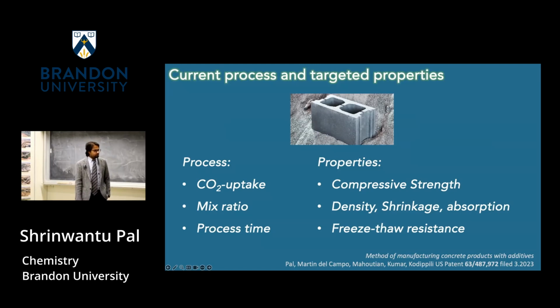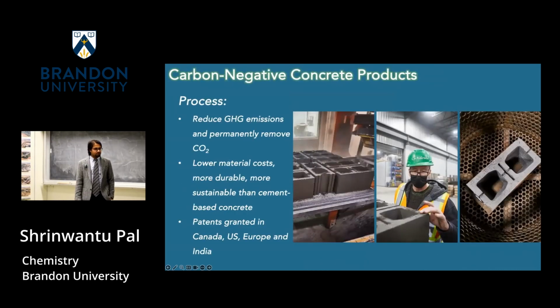And before moving to Montreal, the only place I spent time within Canada was Vancouver, where freeze-thaw resistance is not that big of an issue, but in Quebec, it is a big thing. So for Quebec regulations to be passed, there was something called freeze-thaw resistance, where you essentially take a sample concrete block and you freeze it, you thaw it, you do it over time, and you see how it resists degradation. And thankfully, with the new technology that we filed a patent on earlier this year, it took us about a year to write that patent, but nonetheless, all these three things were addressed, and that basically concludes my talk today.